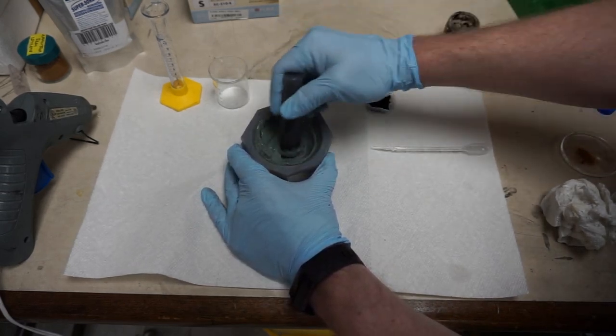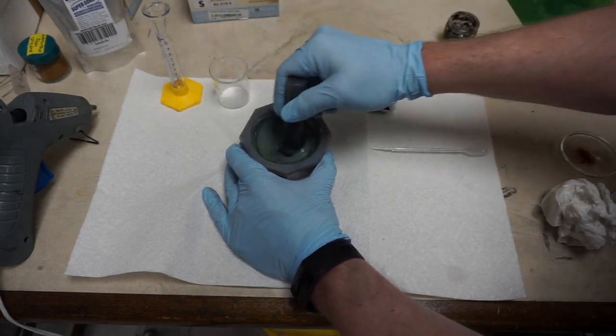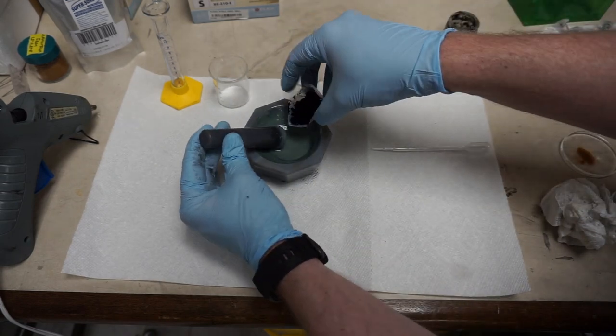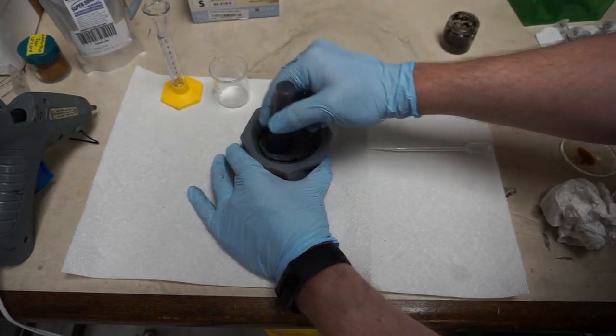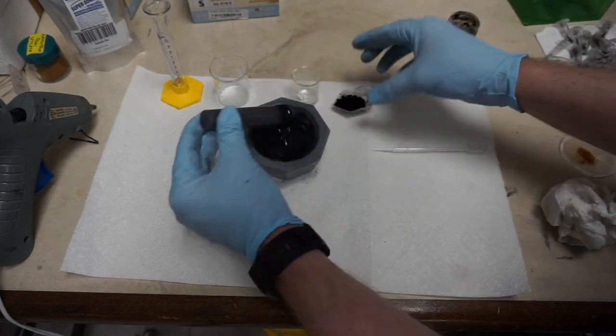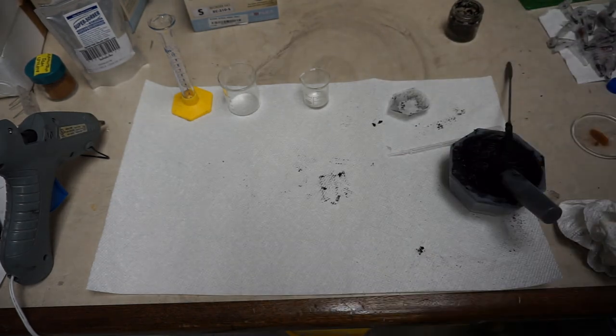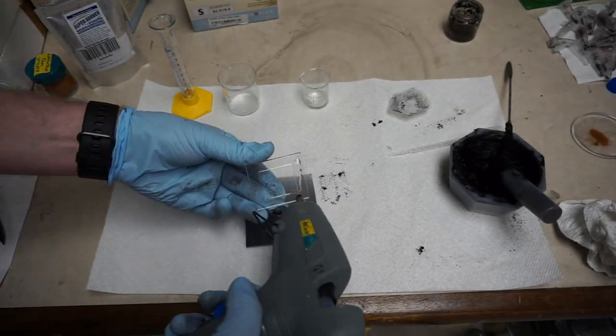Now I'm going to macerate the iron oxide hydroxide. It's in a 2 oxidation state, which you can tell because of that green color. Next, I'm going to incorporate as best I can 0.4 grams of conductive carbon black that has been ball milled to a fine consistency, and then that makes a black paste.